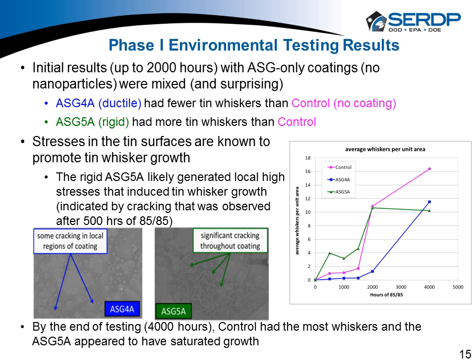When we started into this, based on the early work looking at the materials, we picked two different types of liquid glass or alkali silica glasses. And you'll hear me talk about these ASG4, which was a little more ductile formulation, the way that the team looked at it. It didn't put as much stress into the substrate it was sitting on. And then we also looked at ASG5. And ASG5 was a little more stressful coating, but ASG5 also gave us better environmental robustness. Oxygen, moisture, things would not move through it, diffuse through it nearly as readily as ASG4. So it gave us a kind of two different angles to look at that.